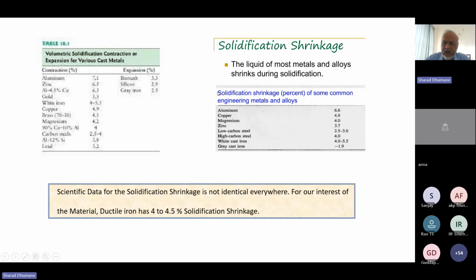reference from another site, solidification shrinkage of different materials. So aluminum 6.6, copper 4.9, magnesium is 4, zinc 3.7, low carbon steel 2.5 to 3, high carbon steel 4, things like that. So scientific data for solidification shrinkage is not identical everywhere. So that is what I would like to mention. But it is fairly in the range of 4 to 5%. And that is what we should understand, keep it in mind and move ahead. Okay.